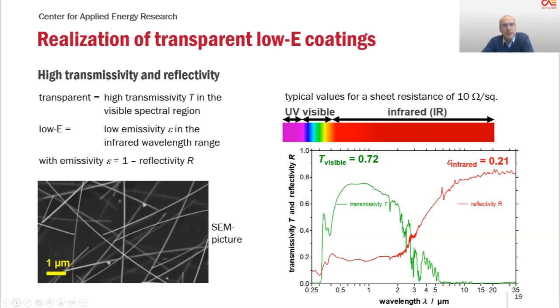So next, please. Here you see again an SEM picture or scanning electron microscope picture of the silver nanowire coating. And as already mentioned by Oliver Zech, the connection between the silver nanowires provides high electrical conductivity and additionally reflectivity of the infrared radiation. That means wavelengths above 5 microns are reflected by this structure, whereas wavelengths below 1 micron or below 800 nanometers, that means the visible spectral region, are transmitted through this structure, as the distances between the wires are larger than 1 micron and therefore provide a high transmissivity in the visible spectral region.